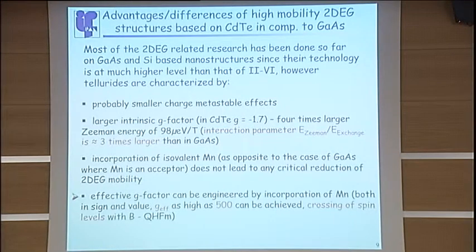Now, moving to the main subject of my talk, the two-dimensional electron gas. As you might have noticed at this conference, until recently, not including graphene, most of the research has been done on 2DEG. 2DEG was performed on gallium arsenide or silicon-based nanostructures because the technology is much better developed. And with respect to those, the probable advantages of our system are that they should have smaller charge metastable effects, which make trouble in III-V. They definitely have a larger intrinsic g factor.